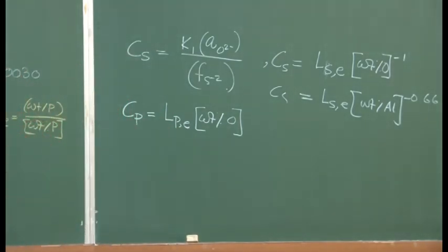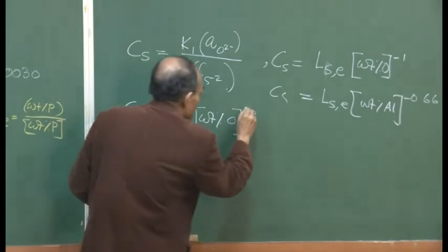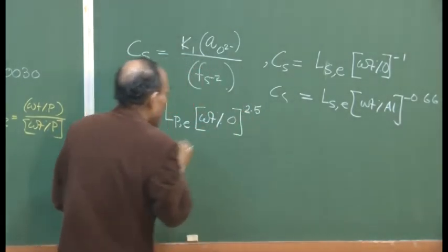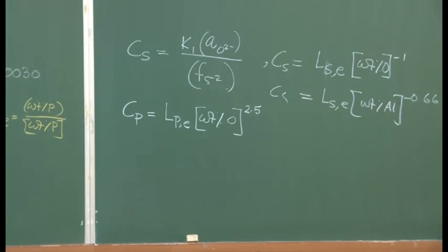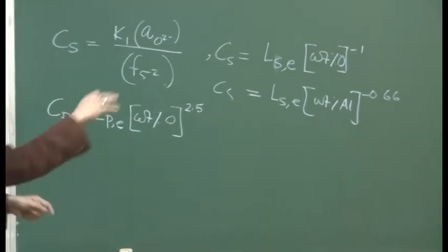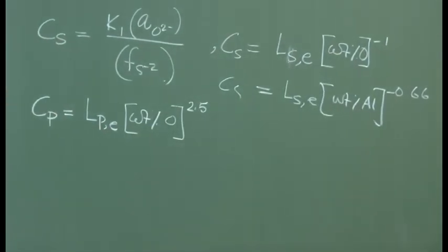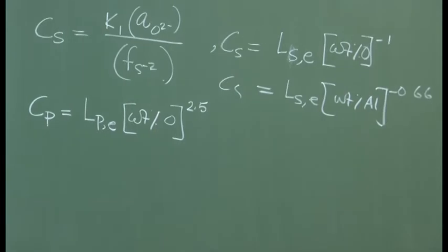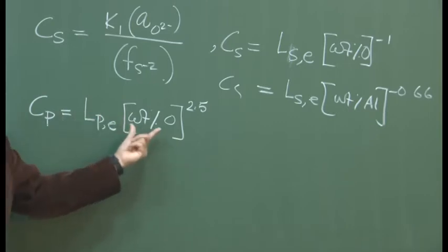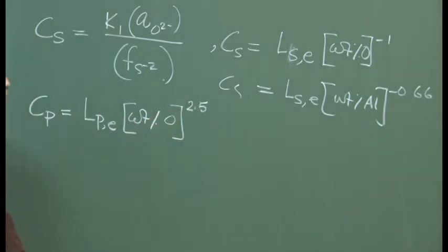increased oxygen content of the material. So, this is going to be equal to 2.5, and that shows the different relationships here. You can see one is inversely proportional to oxygen, the other is directly proportional to oxygen, and then you can see what is the power, and this essentially tells that phosphate capacity is a strong function because the power is 2.5, not just 1, okay, on oxygen itself. So, this is a very popular definition of phosphate capacity, and the phosphate capacity I think